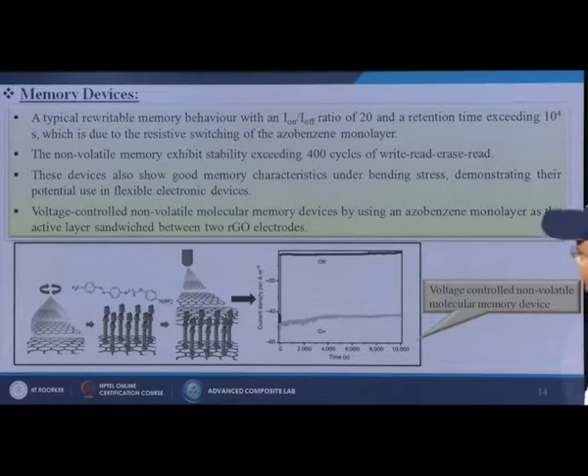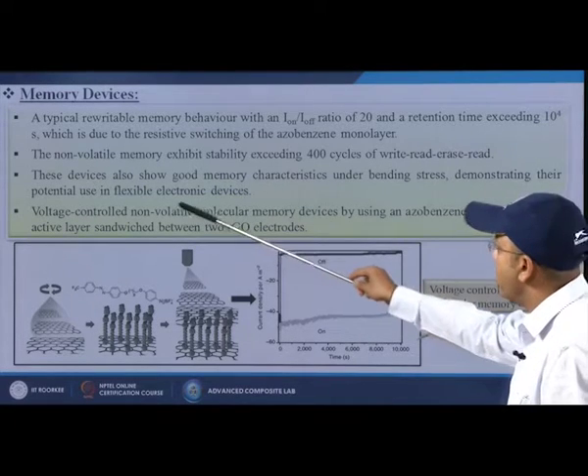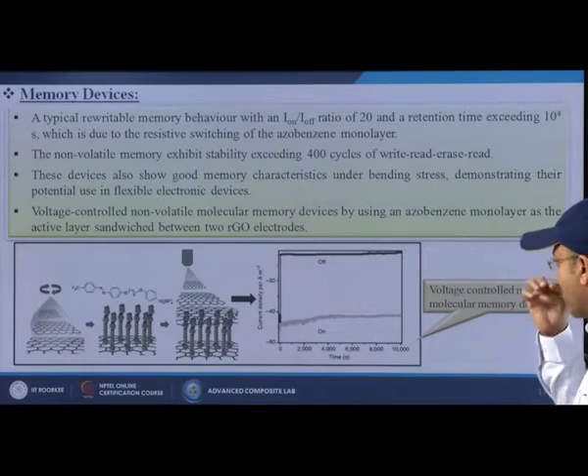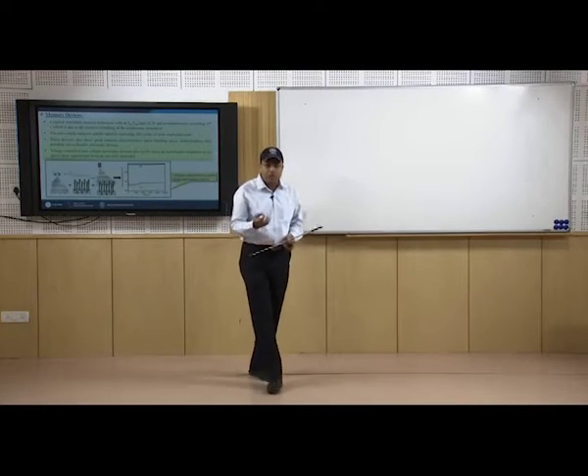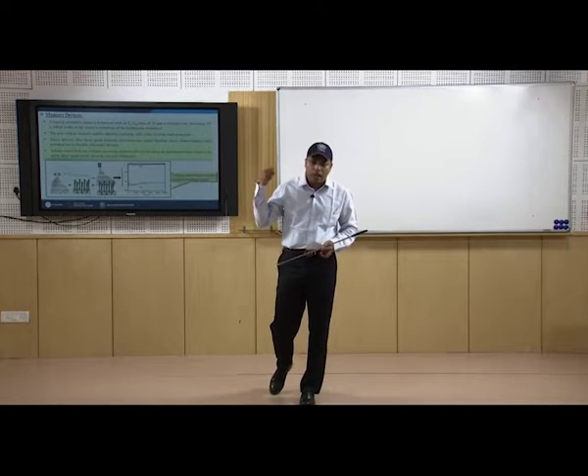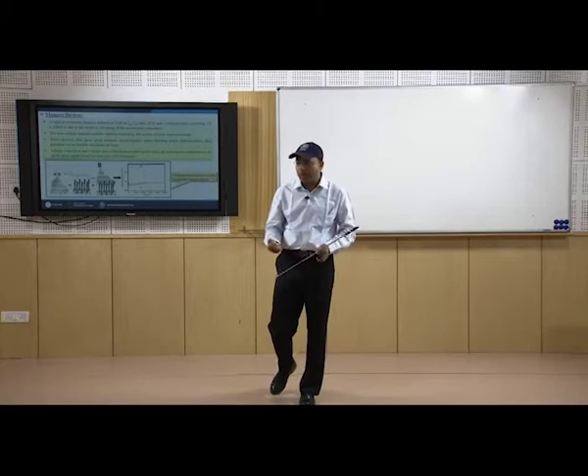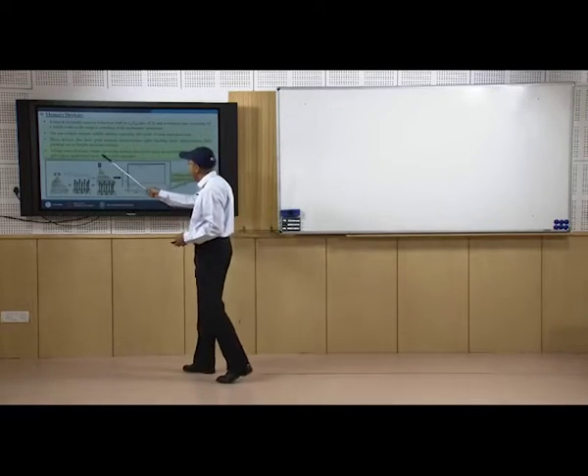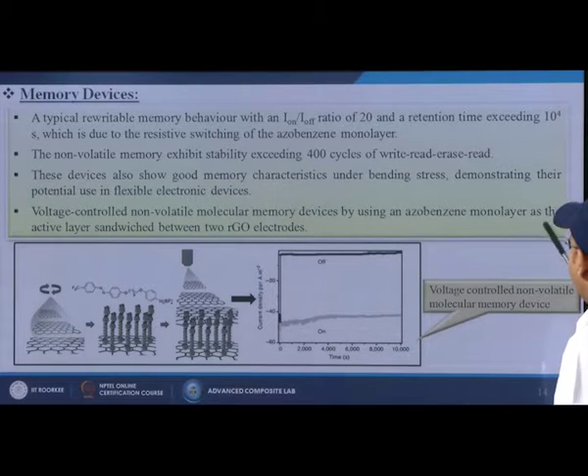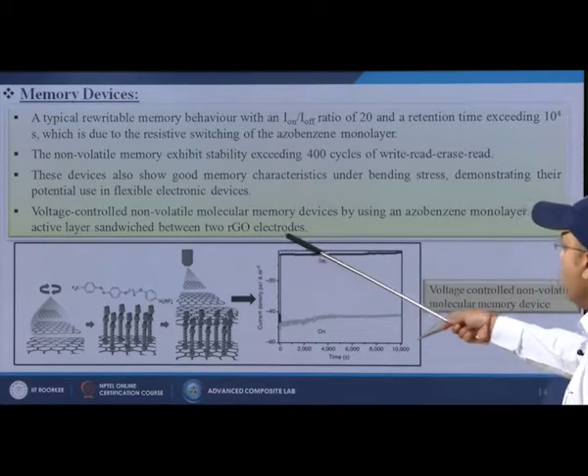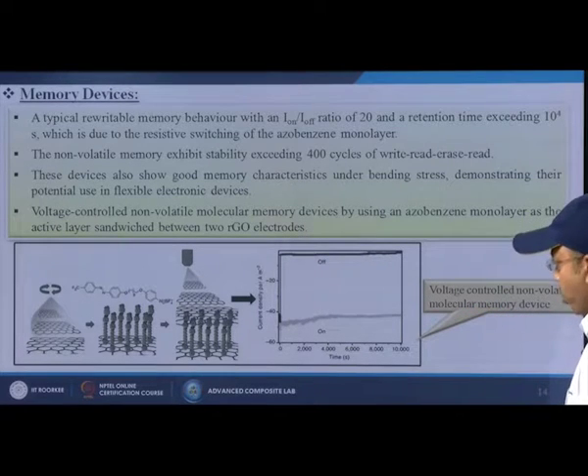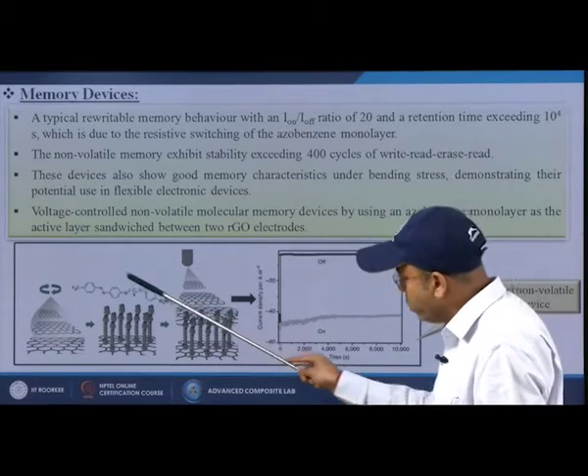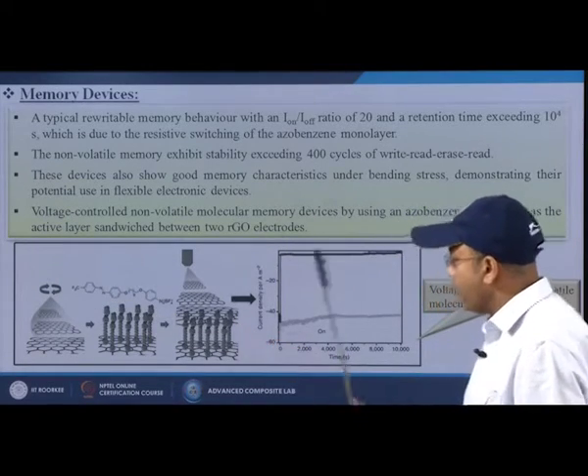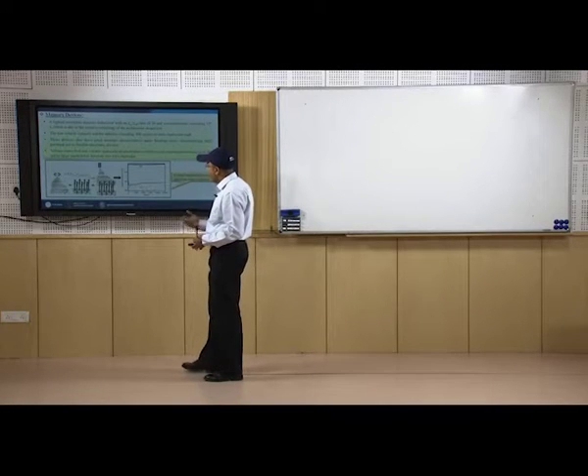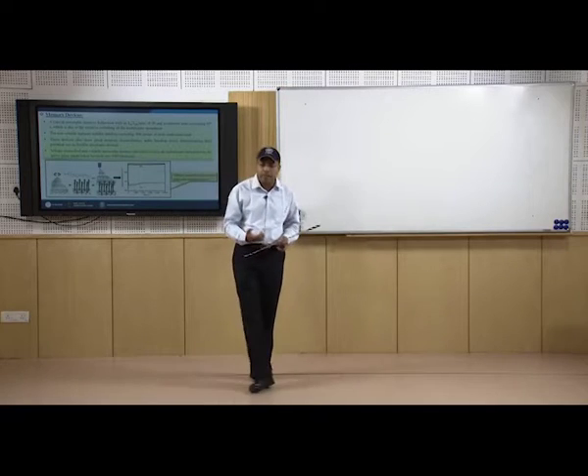Not only that, these devices also show good memory characteristics under bending stress, demonstrating their potential use in flexible electronic devices. So, I can use this kind of material for purposes where some mechanical load or pressure can be applied, but the material will not be damaged. Also, a voltage-controlled non-volatile molecular memory device can be made by using an azobenzene monolayer as the active layer sandwiched between two reduced graphene oxide electrodes. So, here we are putting certain functionalized groups on these materials, so that their memory or storage capability is increased.